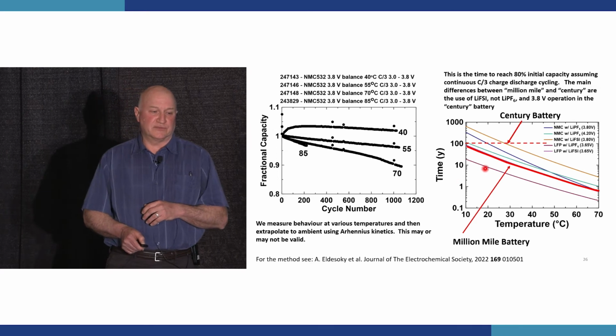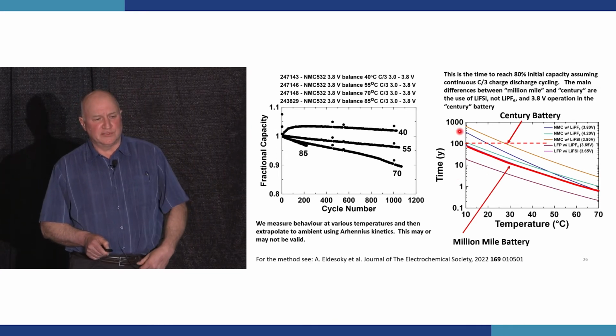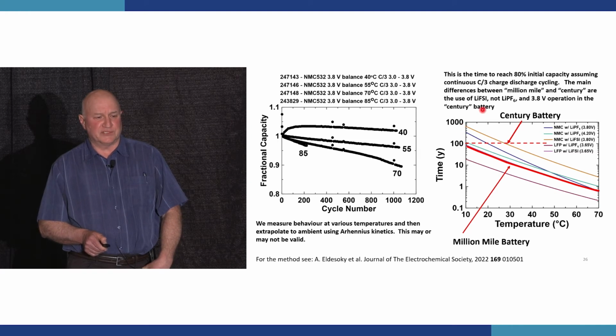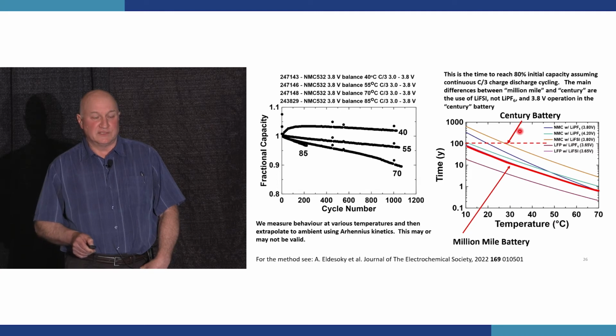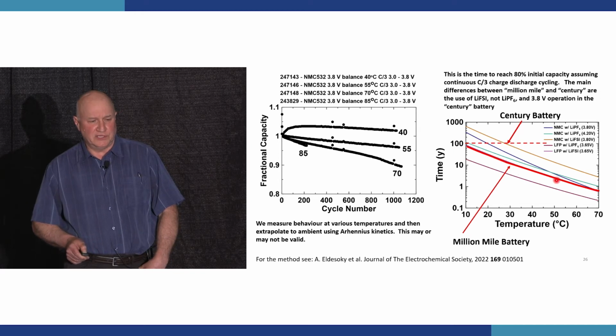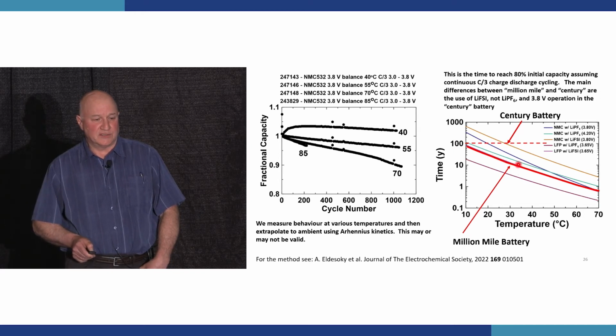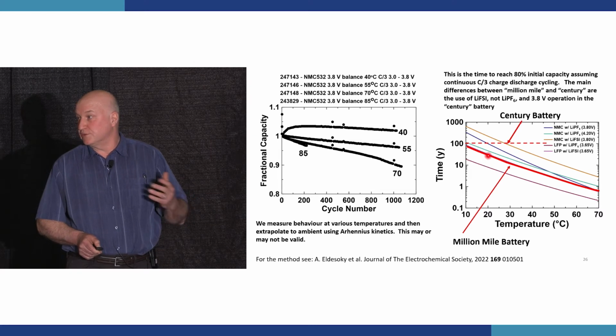So in this graph here, I show you the time that it would take for the battery to reach 80% of its initial capacity, assuming continuous C/3 charge and discharge cycling, plotted as a function of temperature, for different cell chemistries, okay? So the million-mile battery that we started this talk speaking about is shown here in this heavy line. So at about 20 degrees C, it would last 20 or 30 years, which is consistent with the lifetime projections